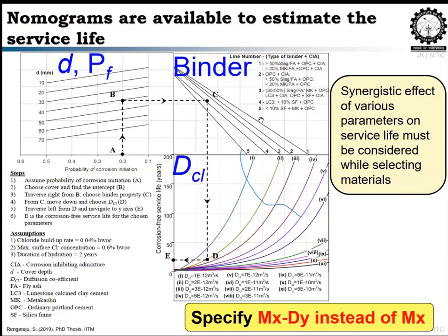Here in this case, I have chosen type 4, which has low lime calcined clay cement of less than 10%, and which has silica fume like OPC. Now with this available binder, what quality of concrete do I have to make to get an expected service life of 25 years? I have to choose the diffusion coefficient like number 2, which is 2 into 10 power of minus 12 meters square per second. That is the unit given for the diffusion coefficient. Now the concrete engineer, with the availability of materials, has to make trial and error to achieve this 2 into 10 power minus 12 meters square per second of chloride diffusion, so that you can ensure you will be getting 25 years of chloride-free service.